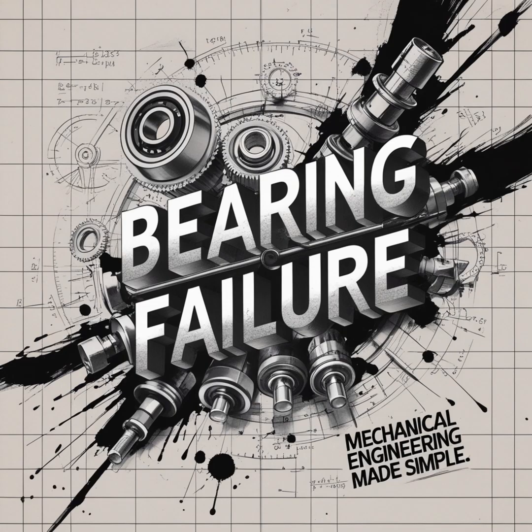Okay, so that's the faulty start. But what if the bearing survives installation and then it fails six months, maybe a year later? Then we're looking at operational damage. What categories are consistently responsible there during the service period? The top two culprits in operation by a huge margin are ineffective lubrication and ineffective sealing. Which I guess leads directly to contamination. They're two sides of the same coin. After that, we look at operational misalignment, which might develop as the machine settles. And then you get into things like the passage of electric current and damage from static vibration.